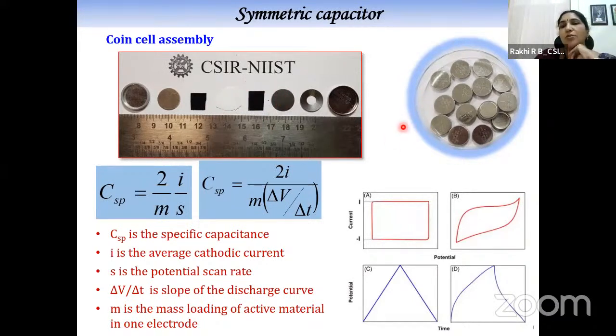And when we talk about the supercapacitor measurements, two important measurements are cyclic voltammetric measurements and galvanostatic charge discharge, which are shown on the right hand side. A and B show the cyclic voltammogram. For an ideal supercapacitor, we should get a rectangle. For a perfectly EDLC type of supercapacitor, we should get a rectangle in the CV curve. But in the real case, there will be deviation. It will be quasi-rectangular in shape.